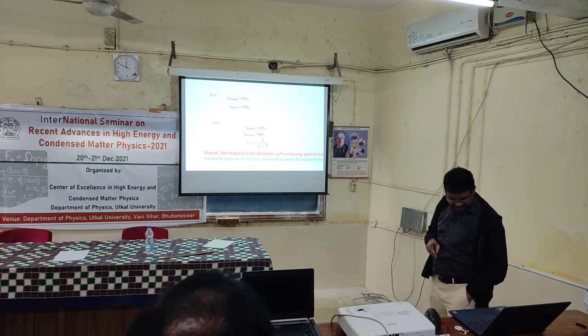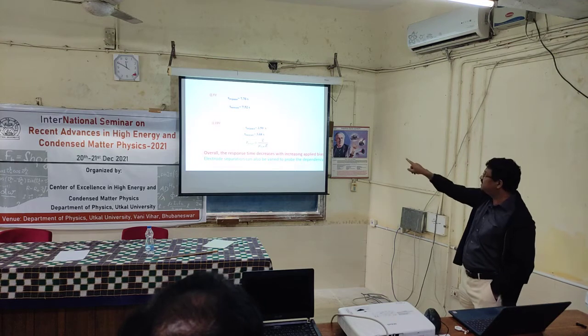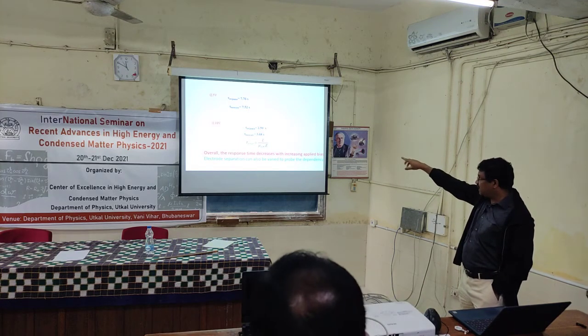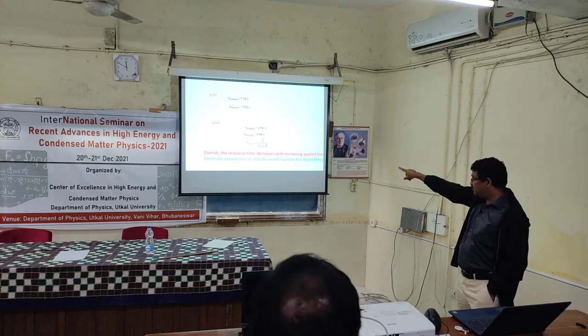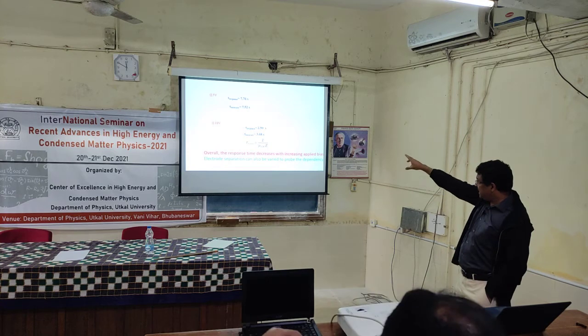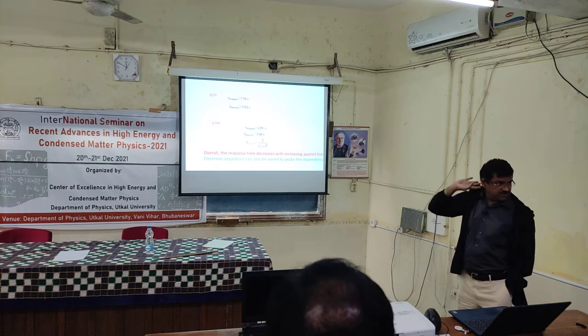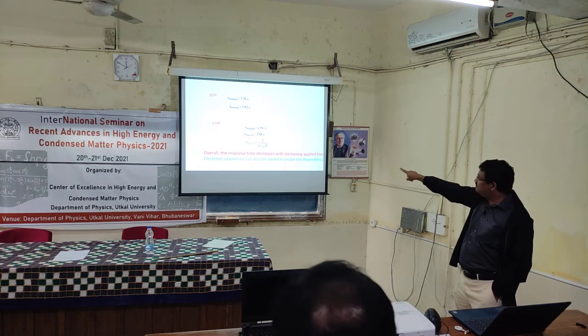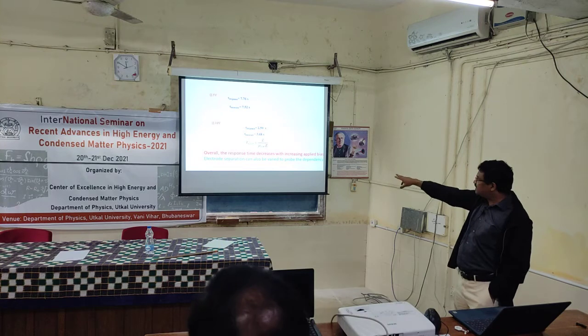So these are the response and recovery times for this SnSe2-based linear device. 7.76 seconds is the response time, and the recovery time is 7.52. At 10 volts, 2.5 and 3.7. What it means is that as you increase the applied bias, the response time is much faster, which is in accordance with the equation. The transit time is equal to length over velocity, and so overall the response time decreases with increasing applied bias.